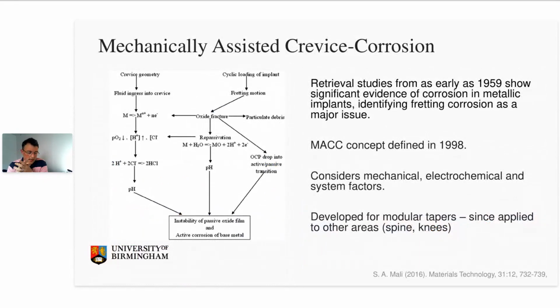Particularly in the case of medical devices, components are usually accompanied by the establishment of a crevice, mainly because of how components are put together and how things are clamped. And what we typically see is that once we have fretting being initiated, we see this elevation in the current, as we saw from the previous slide. But when we cease fretting, that current is usually sustained. This concept was coined in the late 90s by Gilbert as mechanically assisted corrosion, and it's kind of stuck in this area, which gives it a framework that we can apply to these devices, which describes this interaction between both the mechanics and the crevice corrosion that's occurring within these interfaces.